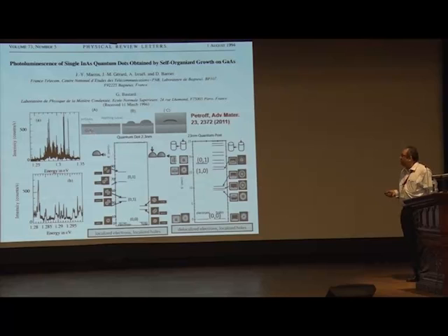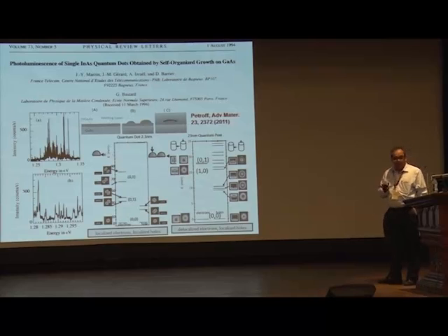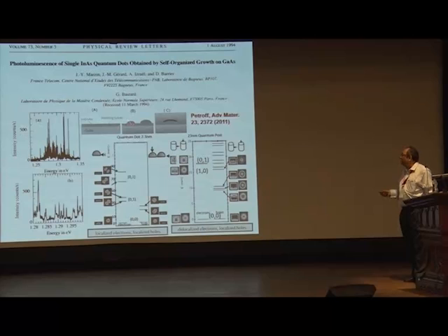Essentially, you take a gallium arsenide substrate in an ultra high vacuum chamber and deposit indium on that, maybe just slightly less than the monolayer required to cover the substrate. The strain develops because of the lattice mismatch, and finally they form this kind of dots on the gallium arsenide substrate.